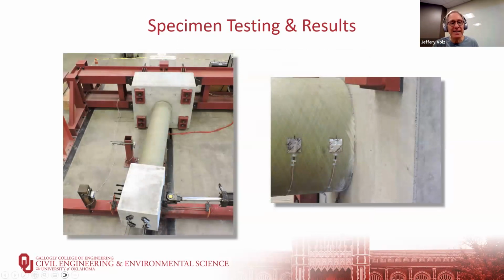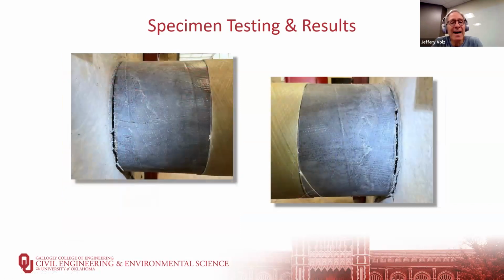Then we get to the UHPC column, same kind of thing. You can hear it breaking, but you can't see it. Here's the column pushed all the way over. Here, the FRP has not split as much at the same displacement, the same cycling. That might be because the UHPC is providing more confinement. And then when we cut the FRP away, you can see that the UHPC is in phenomenal shape. There is cracking. There is some more cracking here, but you really have to look hard to find it. And there is literally no spalling. It is staying fairly intact.